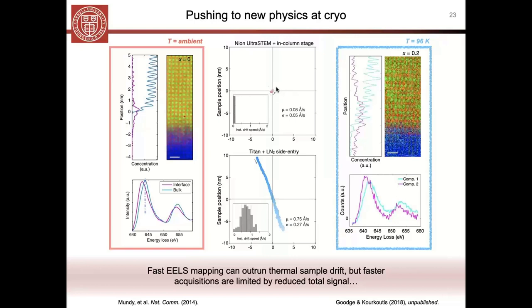So here's that same sample position plot, right? But now you can see that the mean instantaneous velocity on this in-column stage is something like an order of magnitude slower than the instantaneous velocity we have once we move to both side entry, but especially to these in situ cryogenic conditions. And so that is really what's limiting those different velocities, and that different time scale is really limiting our measurements under cryogenic in situ conditions at this point.